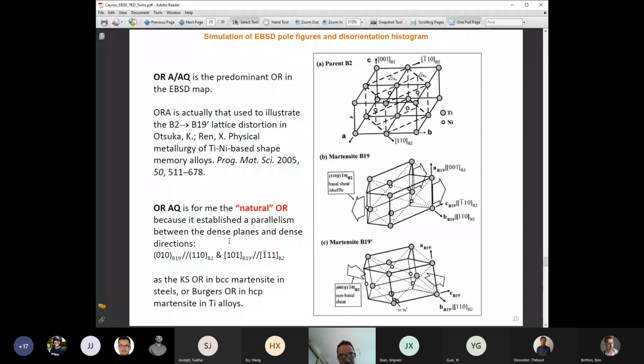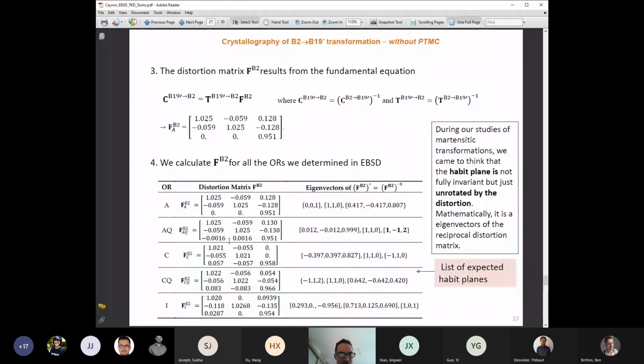I just skip this slide to tell you that from this orientation and from the correspondence matrix, you can calculate the distortion matrix corresponding to the transformation from B2 to B19 prime. It's the distortion matrix F, F from B2. But you can calculate this distortion matrix for the different orientation relationships we found.